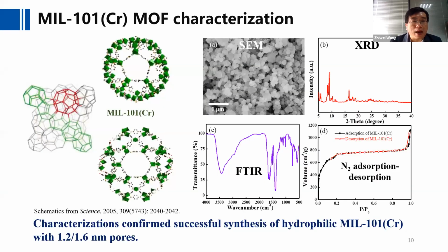First we prepared the MOF material. It's MIL-101, a kind of chromium-based MOF material. After preparation, we used SEM, XRD, and FTIR to characterize the MOF materials. The results showed that we successfully synthesized hydrophilic MIL-101 MOF particles with pore openings of about 1.2 and 1.6 nanometers.